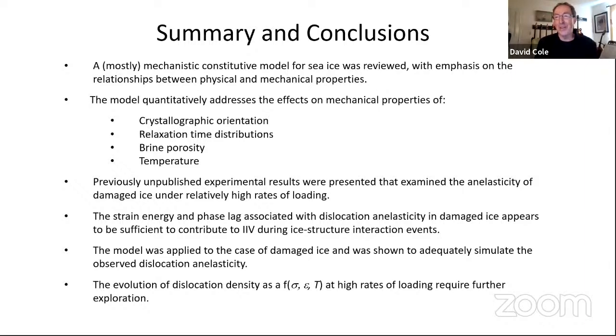Basically, let's consider a breakpoint between scale-dependent processes and scale-independent processes. If you're talking, let's say, mode 1 fracture of sea ice, it's highly scale-dependent, and what you find at small scale can sometimes be connected to large scale, but it's not given, and you really need to do the large scale experiments to find out what's going on. It turns out that the constitutive behavior that my model captures is relatively scale independent.